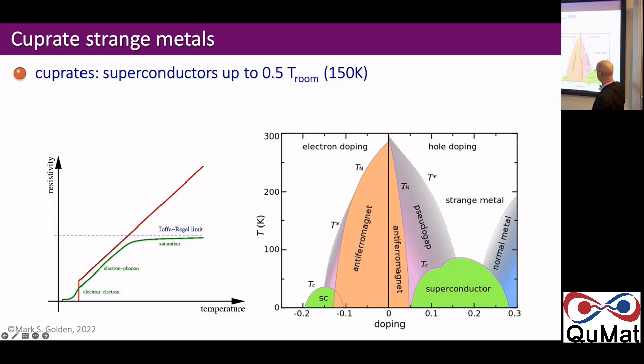So at low temperatures, you have a superconductor, resistivity is 0. At the transition temperature, the resistivity jumps up to a finite value. And even if this Tc is fairly low, so that this is a low temperature, immediately after the superconducting fluctuations have gone away, the resistivity for some doping levels is perfectly linear. And it goes on being linear.